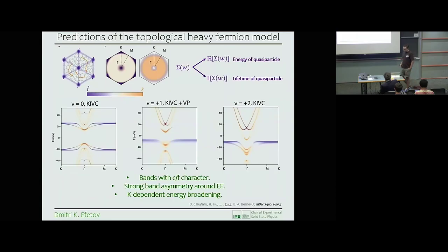So the mass asymmetry comes naturally out of this, but on top of that, and this is again very crucial, these calculations can also provide a measure of the lifetime asymmetry, which is the smearing that you can see here. As you can see in the filling factor 1 and filling factor 2 states, there is a strong smearing of the flat band region of the heavy mass regions, which dramatically reduces the lifetime of these bands.